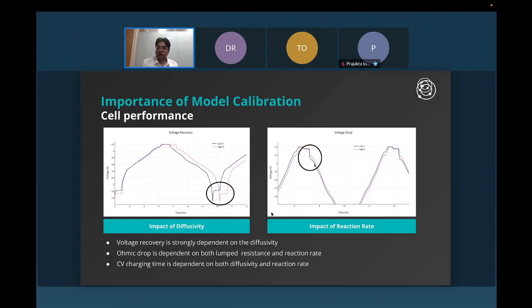the voltage drop depends on the lumped resistance of the cells and also the overpotentials, which are dependent on the reaction rates. And if you don't estimate these properties properly, you are off in estimating these DCIRs, which are again an important parameter for understanding the cell performance. And that basically sets the context for why these parameters need to be determined accurately for any subsequent performance or degradation analysis of these cells.